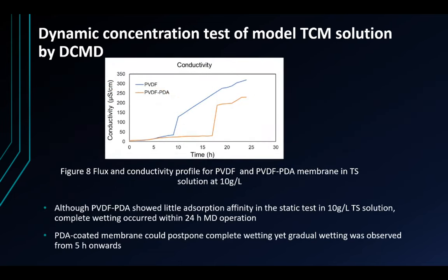We were also interested in the PDA-coated PVDF membrane on the wetting resistance in the TS solution at 10 grams per liter. We found that although PVDF PDA membrane showed little adsorption affinity in the static test in the TS solution, complete wetting was still observed within 24 hours during the MD operation. Wetting initiated at roughly the same time as the PVDF membrane, but PDA coated membrane could postpone complete wetting.